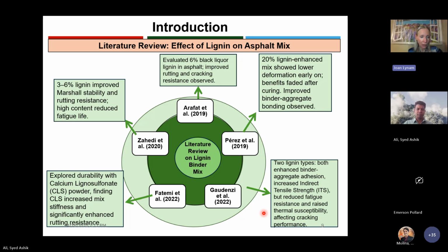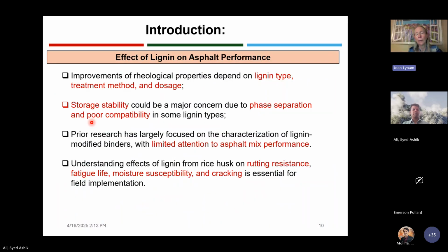If you look at 7 o'clock on this circle, you see that they used calcium lignosulfonate powder. That's something you could probably get from black liquor. So it's another wood-based one. And they found better stiffness and enhanced rutting resistance. Then finally, if you look at Zahedi et al. in their 2020 study, they did get, with a small amount of lignin replacing the regular standard binder, improved Marshall stability and rutting resistance. But eventually, if you had too much, you had lower life.